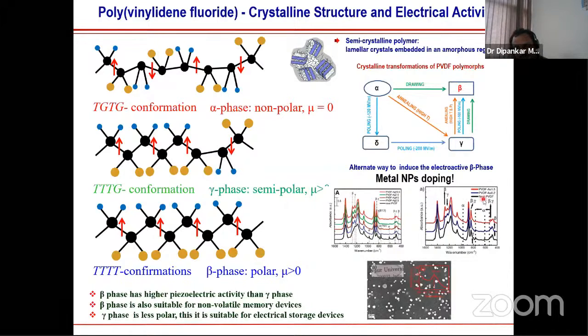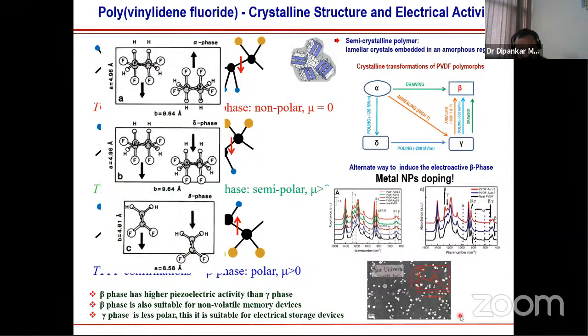Here is another way where we put the gold nanoparticle, and this is without nanoparticle. You can see the alpha phase is there, but once we put the gold nanoparticle, this alpha phase diminishes and the beta phase is going up, right? So this is the surface morphology. You can see the color of the film because of the surface plasmon from the gold nanoparticle. And this is the crystalline lamella. You can see needle-like structure in between, and there are many particles. These are basically gold nanoparticles spread over the surface.